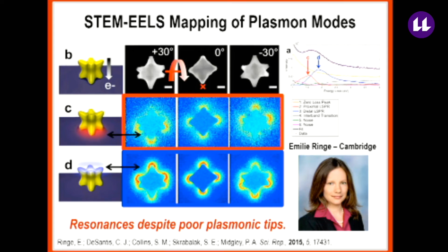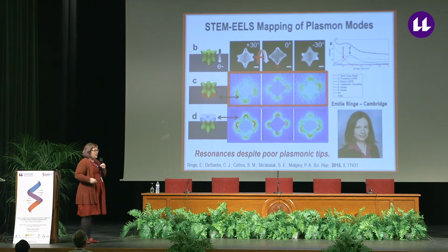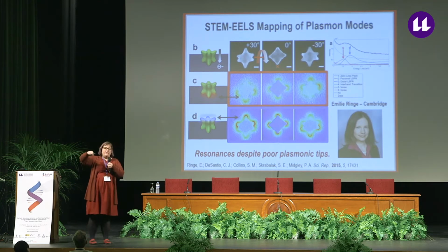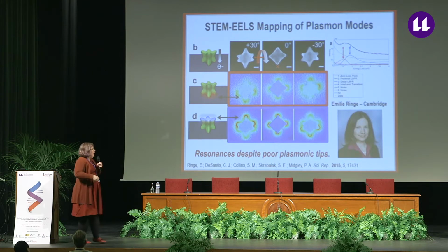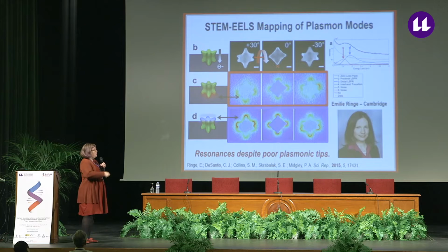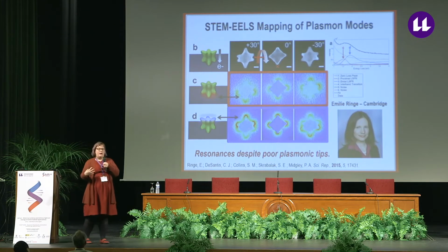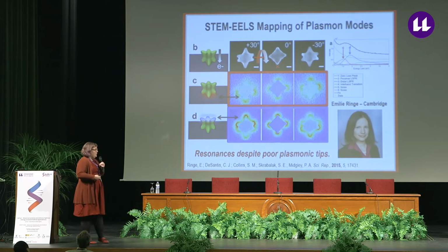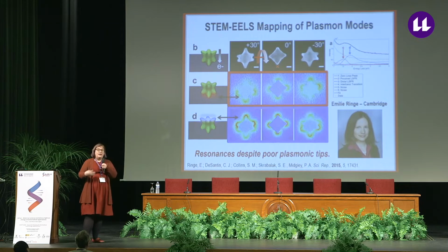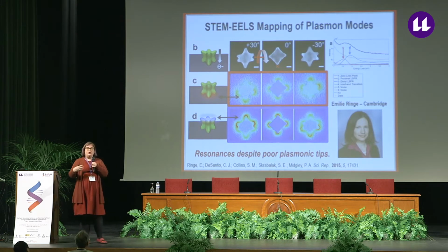And some of the ways in which she studies these nanocrystals is by STEM EELS, electron energy loss spectroscopy, which allows you to map the plasmon modes within an electron microscope under electron excitation. And so shown here are her results obtained with one of our 8-branched octopodal nanocrystals. And what she was able to find was that, indeed, even though we have this poor plasmonic metal palladium at the tips of the nanocrystals, we get this electric field enhancement just like you observe in the gold nanostar cases.